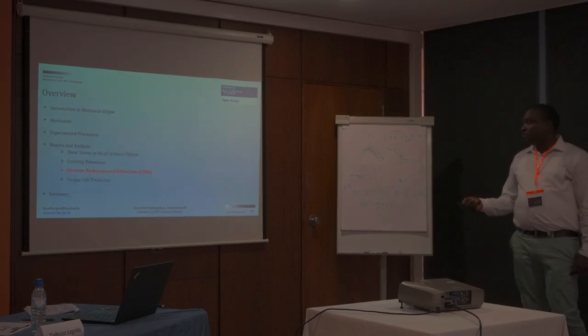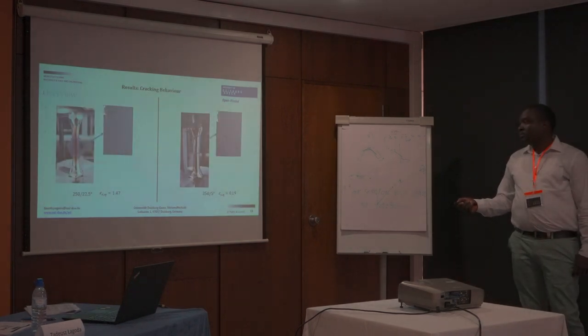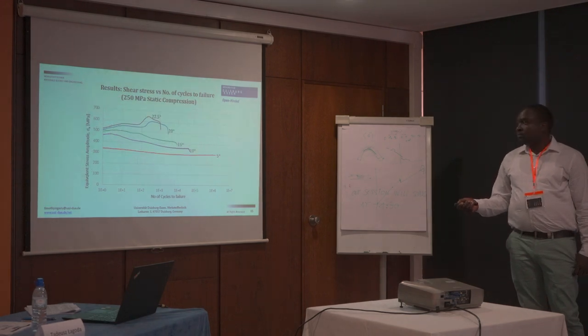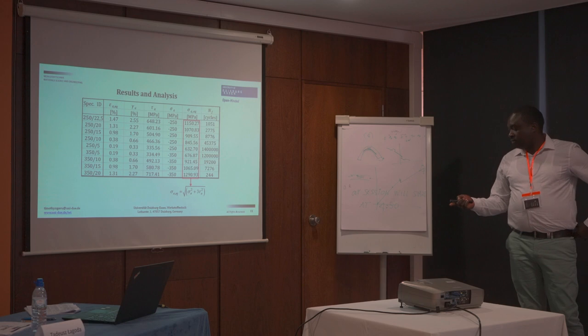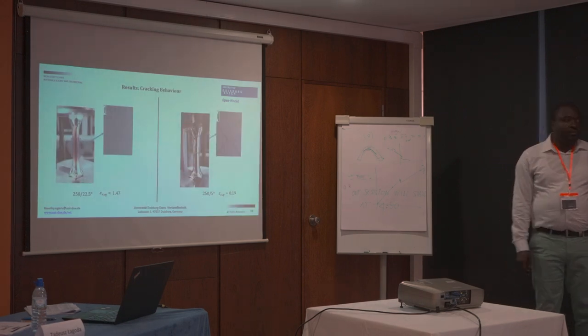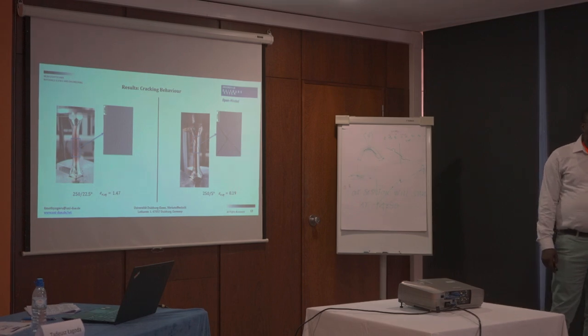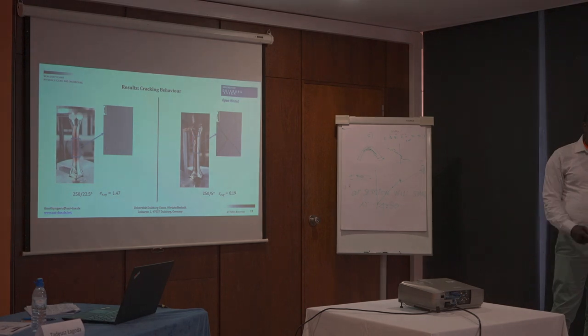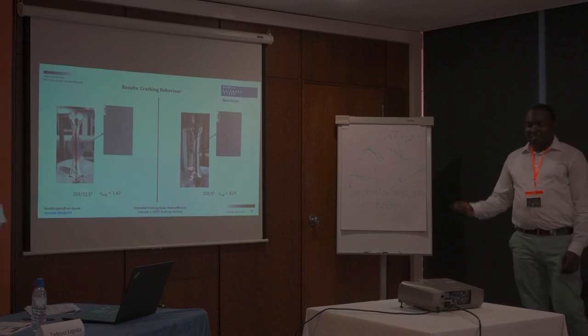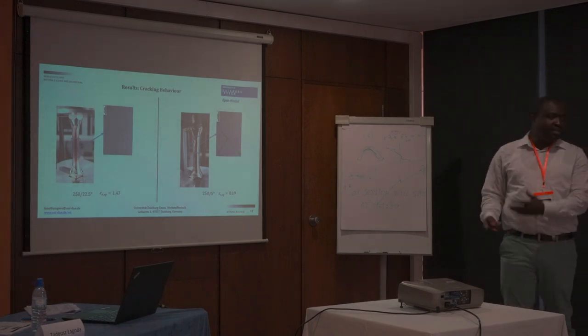If you see the gauge section again, where the gauge section at the end becomes wider again, the discoloring is changing, because there the loading is less, because the cross section is more. Right? But you might want to look into the plastic dissipation in fatigue loading. Yeah, thanks. I wouldn't be too much surprised that it goes up to a few hundred degrees Celsius. 300. Yeah, but as I said, this is my preliminary study, so I'm doing more.